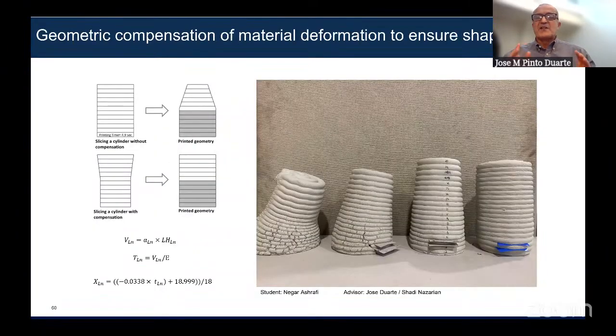The other one is to understand the material behavior. For instance, I mentioned before that when we were printing for the NASA competition, there were two windows very close to each other with a small pillar in between, and we changed the tool path. There are basically two possible strategies. One, you would go around, stop printing, bridge the opening, print the pillar, continue, bridge the other opening, and continue printing. So we changed the tool path at the last minute, so we would print the walls around the windows, and then print the pillar at the end.